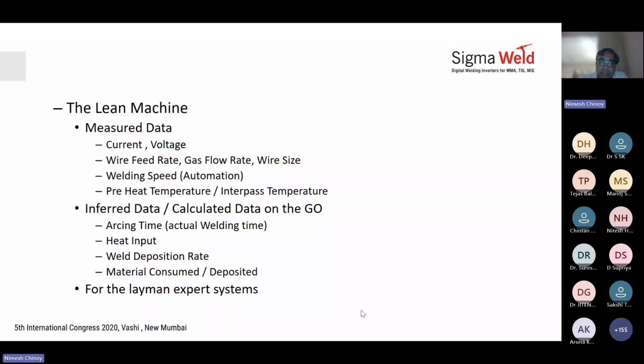What is the heat input? Heat input is basically the current times voltage divided by the speed at which you are moving. So there's a formula around it. It will tell you how much heat input you put onto the job. If the heat input is very high, it can lead to distortion, and sometimes it can even harm the weldability of the material. If the heat input is right or low, you will have lower distortion